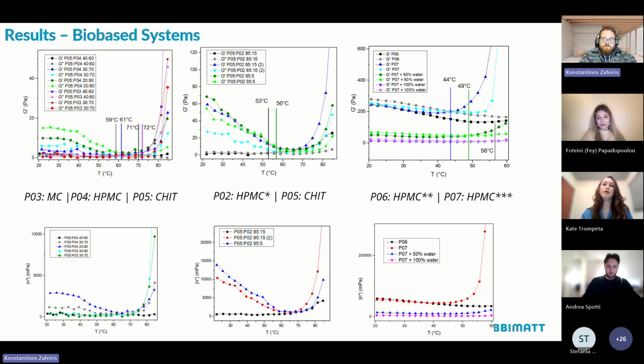Although blending with hydrogel slightly affects this transition behavior, it is not sufficient to shift the lower critical solution temperature into the desired temperature range of our application in the BBIMATT project. Also, on the bottom of the slide, there are some viscosity data that also confirm the trend we referred to before, showing a corresponding increase in the transition point of the hydrogels. So overall, while fully bio-based systems are proven to be thermoresponsive, their transition temperature is too high for our application, highlighting that we need to experiment even further with our design strategy.